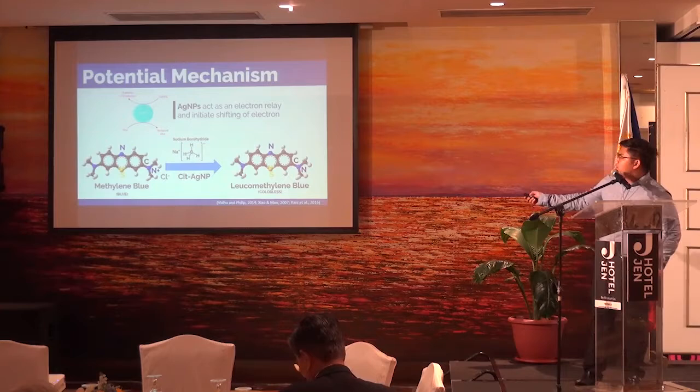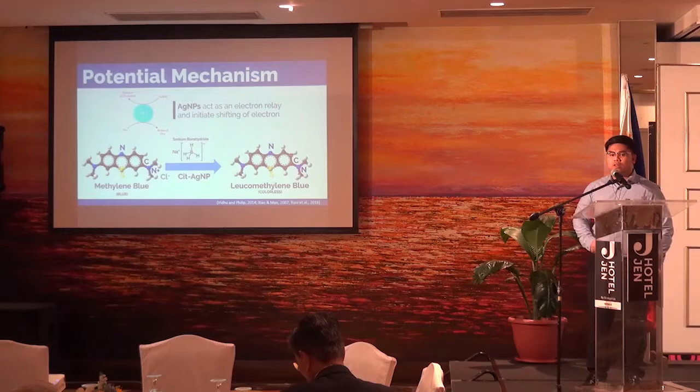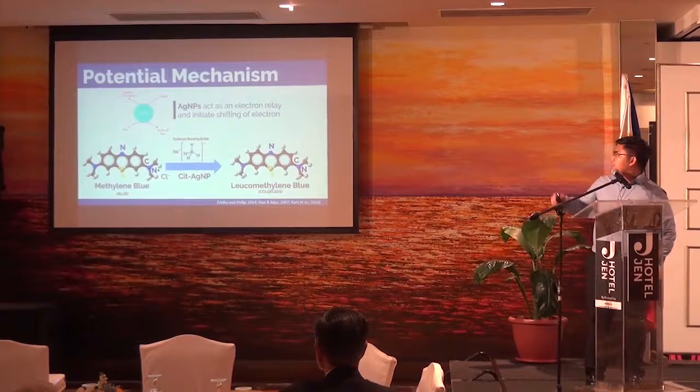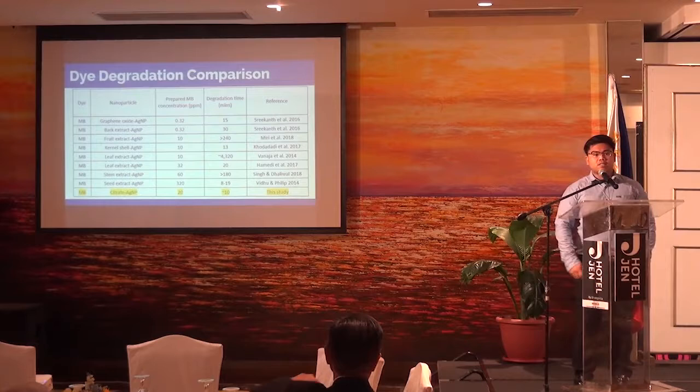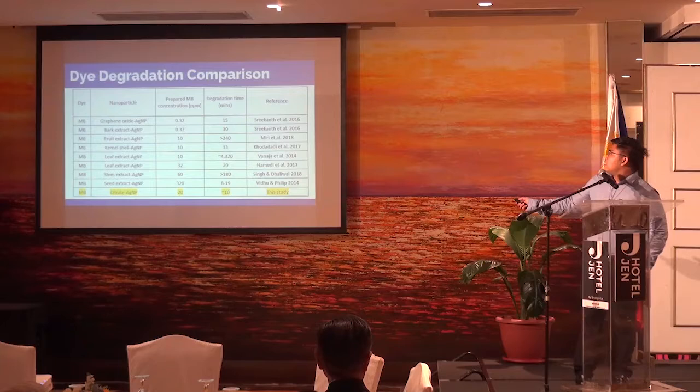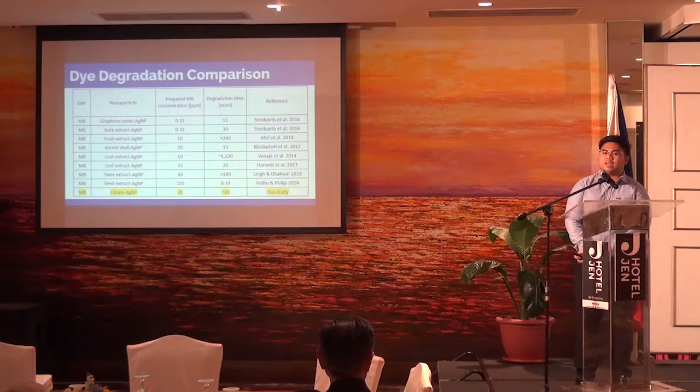For the potential mechanism or the chemical reactions within my study: we have methylene blue added with the reducing agent sodium borohydride, then the citrate-stabilized silver nanoparticle catalyst reduces the methylene blue into leucomethylene blue, which is a colorless solution. The citrate agent acts as the electron relay for the electron shifting. Comparing our results to other studies, at 20 ppm we have already degraded the sample at about 94% in only 10 minutes, so it is effective. Furthermore, citrate-stabilized silver nanoparticles are easier to synthesize than alternatives.